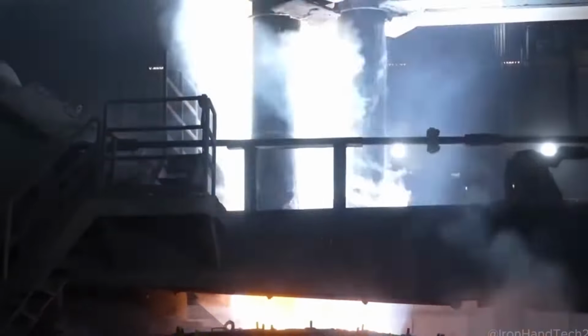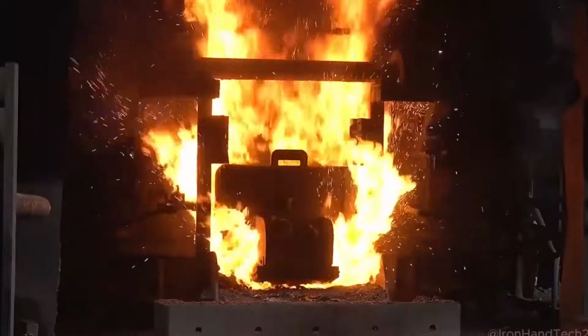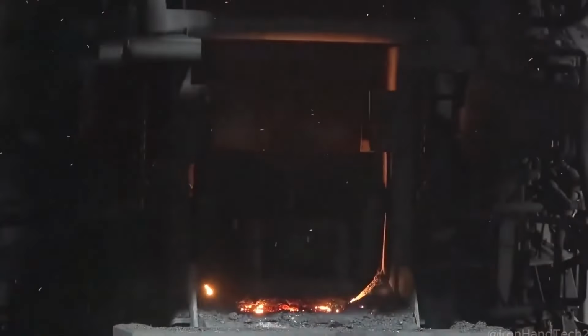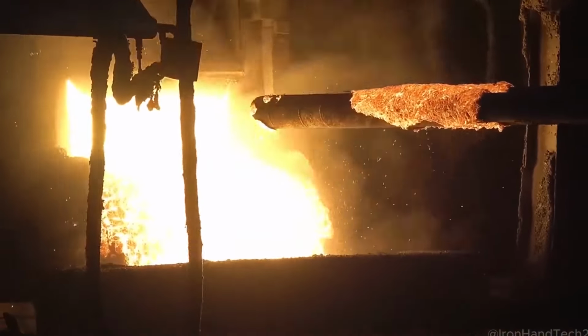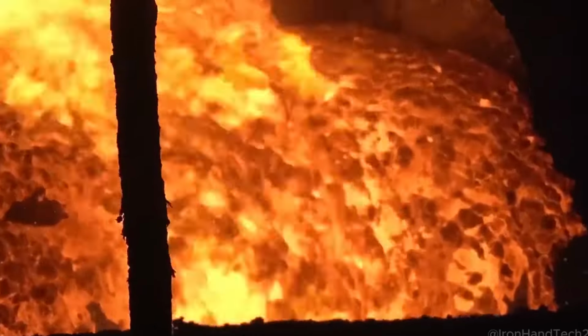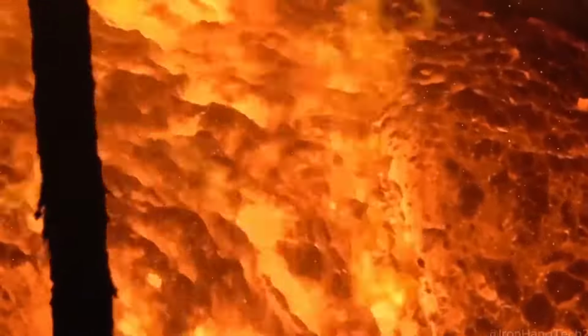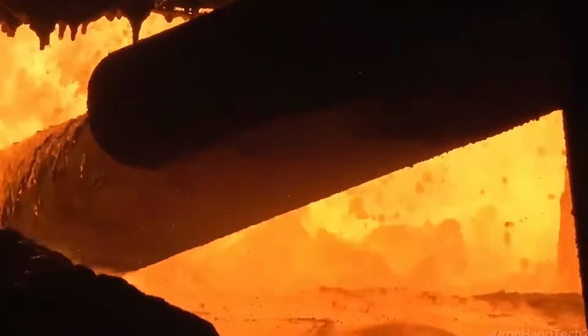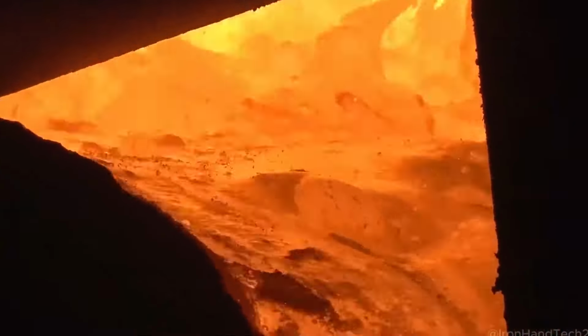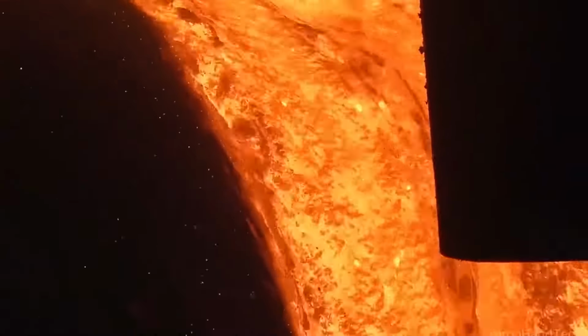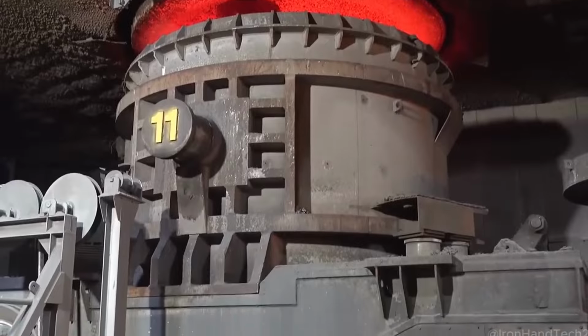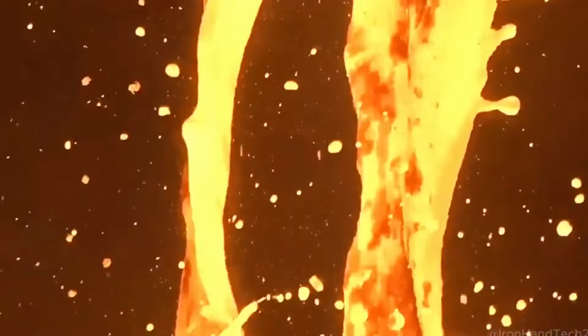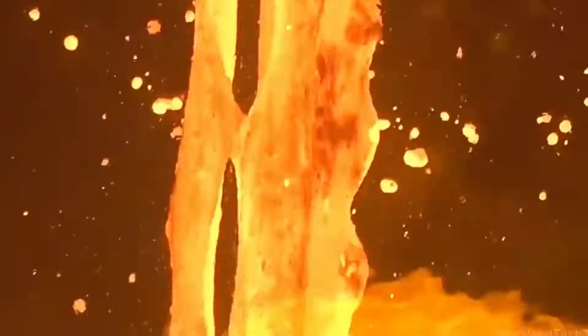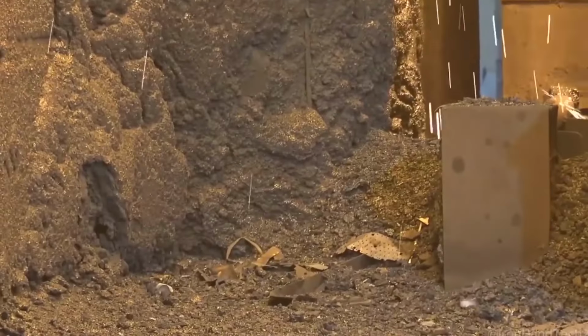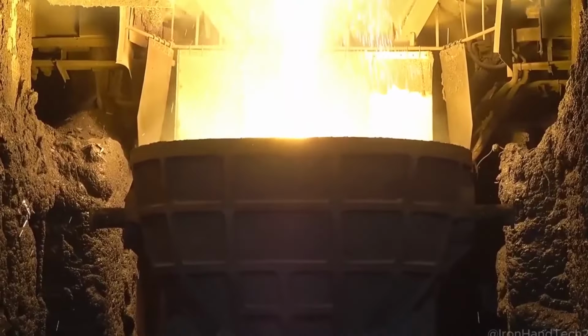As the steel melts, unwanted materials like dirt, plastic, and paint burn off or separate, forming a foamy layer of slag that floats to the surface. But even this isn't wasted. It's collected, cooled, and crushed for use in cement and road construction. Even though electric arc furnaces are a cleaner way to recycle steel, the industry is always looking for ways to improve. Some factories are now replacing coal-based fuel with shredded plastic and rubber, reducing waste while keeping the process just as effective. The steel is melted, but it's not ready yet.